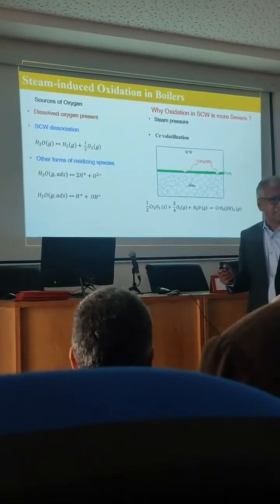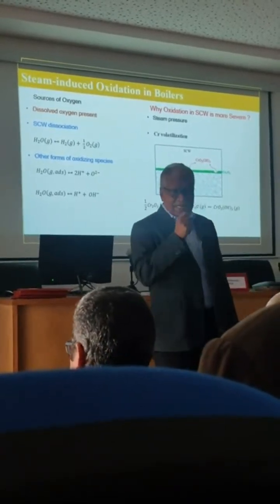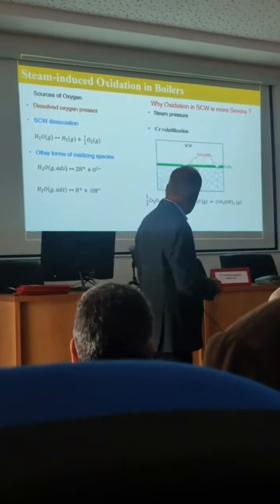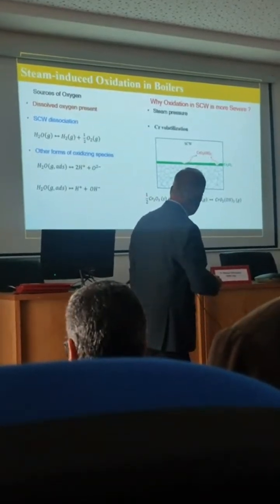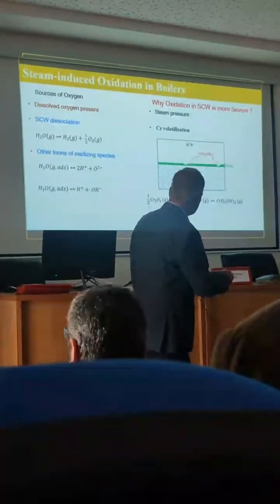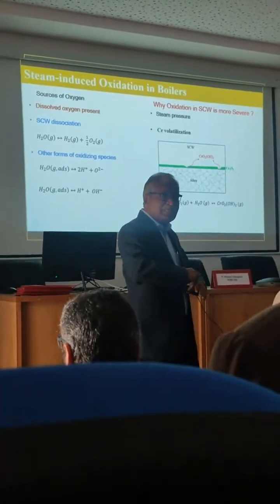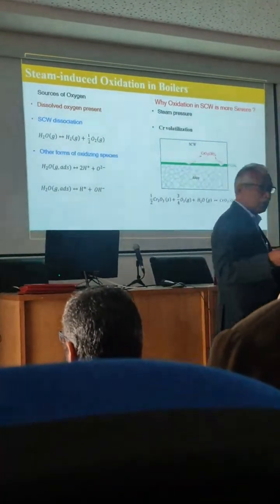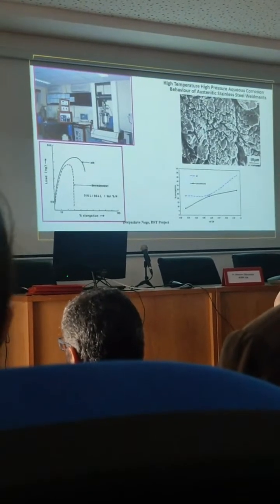Otherwise, the chromium oxide is very good. A lot of stainless steels are being used where the mechanism of corrosion protection is to have the chromium oxide, but at that temperature, the chromium oxide simply evaporates. It's no more good at all for particular applications. So these are the issues that happen, and so we start looking at it now.